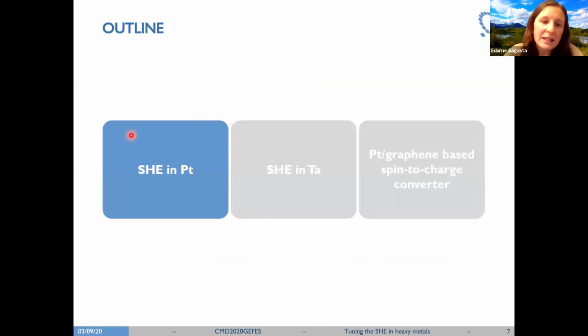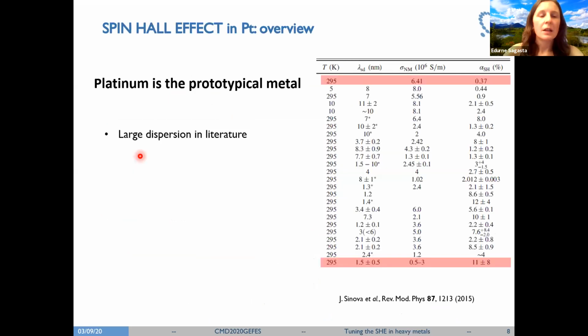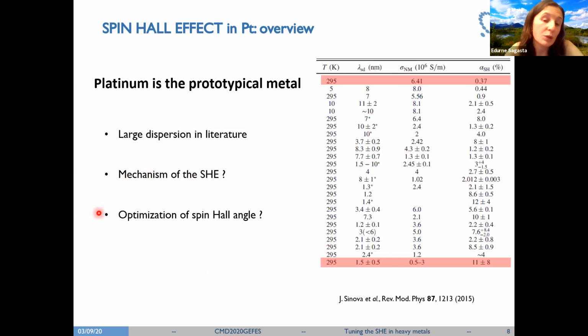So now we will jump to the results and the experiments that we did to study the spin Hall effect in platinum. Platinum is the prototypical metal where the spin Hall effect has been studied. If we go to the literature, we can see that we have many results and the spin Hall angle value varies significantly from group to group and technique to technique. Also, experimentally, it is not clear which mechanism is dominating the spin Hall effect. And of course, this hinders how we can optimize the spin Hall angle, which is in the end one way of enhancing the output voltage that can be useful for applications.